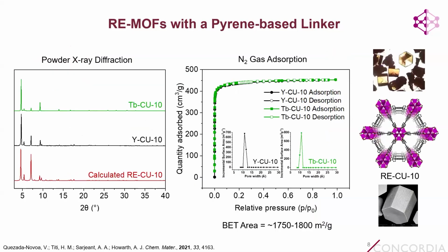And so in addition to those large and beautiful single crystals, Victor was also able to make this material in bulk, so nice microcrystalline powders. So you can see the powder X-ray diffraction patterns here show that the material is crystalline and phase pure. And this MOF also has permanent porosity, so we can activate it under vacuum at 120 degrees Celsius to get these nice type 1 nitrogen gas adsorption isotherms with surface areas of around 1,800 meters squared per gram, showing that these triangular pores are about 10 angstroms in diameter.